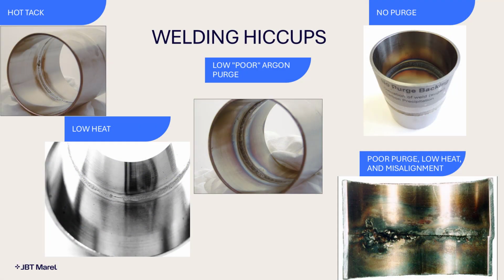Here are some welding hiccups. Like I said in the last slide, you're going to want to pre-purge before you do any tacks. Over here you can see a hot tack was done. Somebody didn't purge the system before tacking it together. They tacked it, they never looked on the inside to see if they penetrated through. And then they put their purge on and they began doing the weld. And you could see the weld looks great, except for that spot where they had the hot tack. That could be easily avoided if the person would have looked in there after he tacked it and used a straight grinder or something of that equivalent to get that hot tack out.